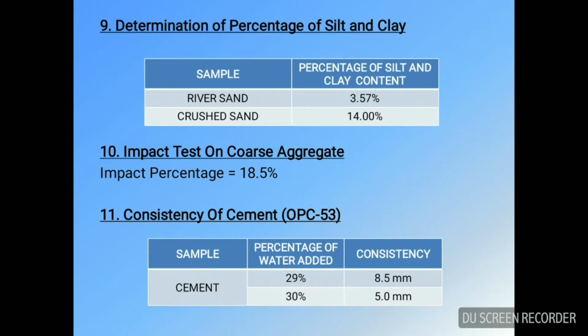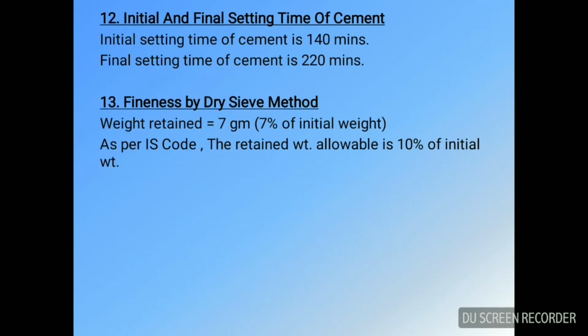Next we did the consistency of cement. For consistency of cement, as you can see here, we got around 29 to 30%, and the depth of penetration came to around 8.5 for 29%, while 5 for 30%. The allowable limit for depth of penetration is 5 to 7, so for 30% we got our allowable limit. Next we did the initial and final setting time of cement. The initial setting time of cement came to be 140 minutes, while the final setting time came to be around 220 minutes.